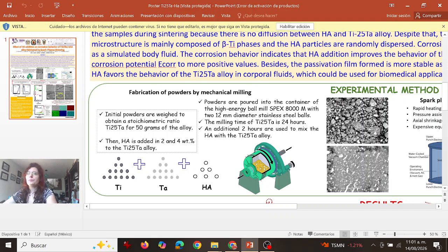All these powders are poured into the container of a high-energy ball mill, SPEX 8000M. Here we have an image of this mill. We add the powders into the container together with two 12mm diameter stainless steel balls. The milling time of the titanium-25 tantalum was 24 hours, and an additional 2 hours were used to mix the hydroxyapatite with the titanium-25 tantalum alloy. All right, that's all for the fabrication of the powders.